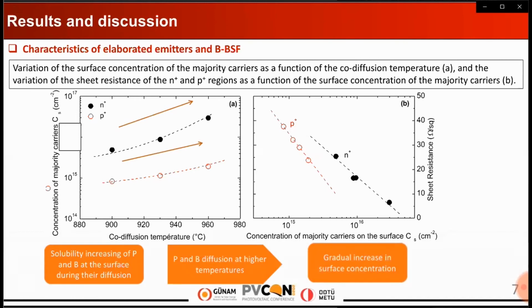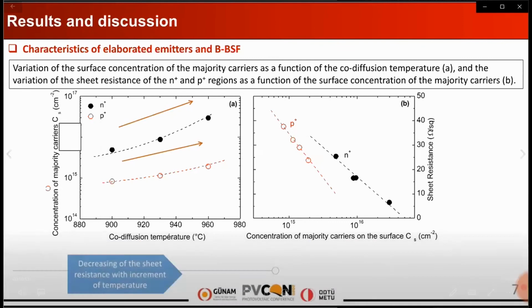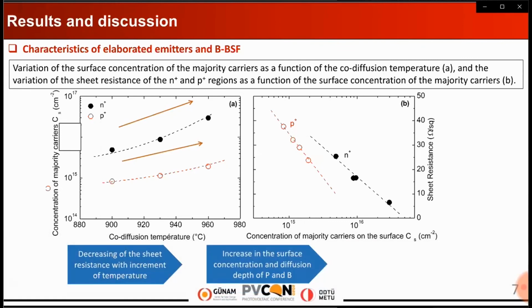The increase of the surface concentration with temperature is due to the increase of the solubility of dopant during their diffusion. The depth of the N plus P and P plus P junctions affects the sheet resistance of N plus and P plus regions. In addition, increasing the surface concentration provokes further decreases in the sheet resistance of the diffused region, as illustrated in the same figures, part B, on the right side. This finding is a proof of the realization of bifacial structures N plus P P plus with different junctions, N plus P and P plus P.